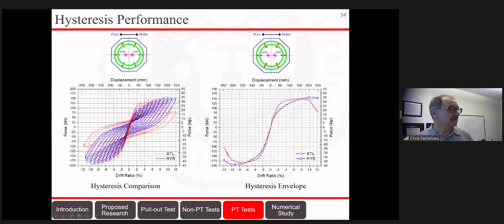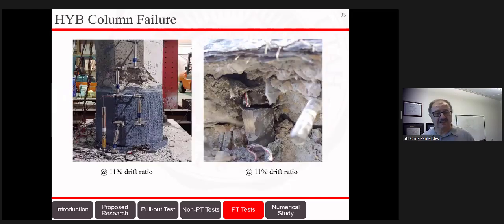Comparing the two, again, you can see the steel is the red and the blue is the hybrid. We can see that they perform very similarly in this case because of the post-tensioning. And the hybrid reached the peak at 10%, whereas the steel column reached a very high capacity at around 7%. So the difference in lateral capacity was less than 5%. And you can see here in the envelope they perform very similarly, although, as I mentioned, the hybrid kept increasing, whereas the steel reached a plateau. Here we can see the hybrid failure.